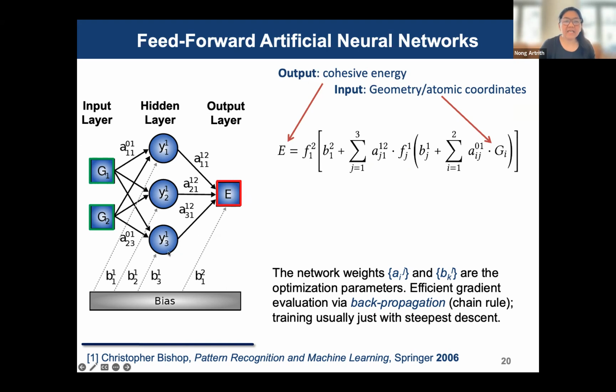In my case, I use artificial neural networks. And then the output we get is the energies. So we try to use a neural network to help find the relationship between the energies and the structures, or structures and energies. And from the derivative, we can also get the forces, and then we can use them in simulations, like Monte Carlo simulation and MD simulation later.